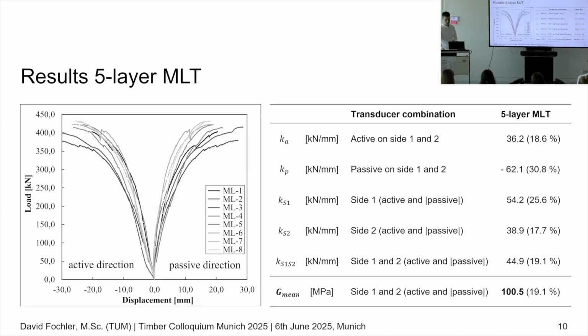And then the last one, the results of the mechanically laminated timber. These tests worked out well, and in all specimens the typical torsion failure of the joints occurred because they were only jointed with nails. But during these tests, the displacement in active direction was much higher than in passive direction. You can see it even here in the graphic. It's a much higher deformation.